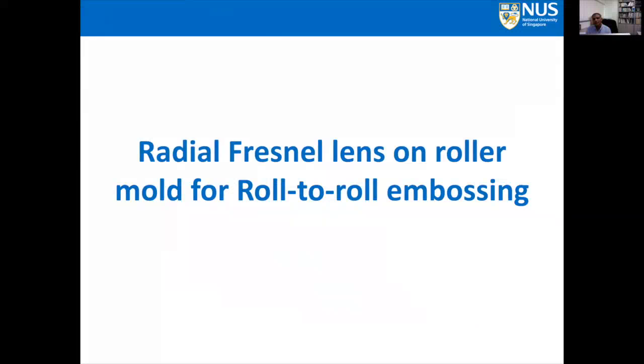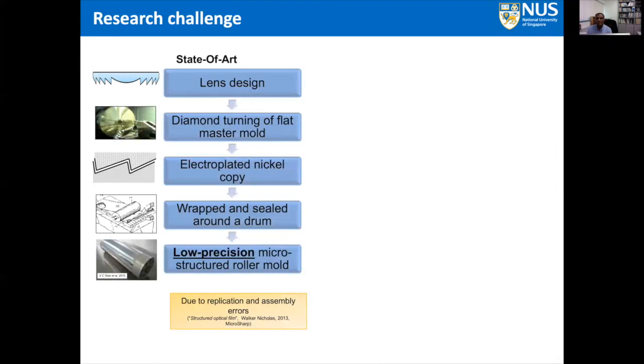So the radial Fresnel lens on roller mold for roll-to-roll embossing is something which is very important to us because now we are directly machining the Fresnel lens on top of a roller and then using that roller for embossing purpose. Therefore, we are able to produce long, continuous Fresnel lenses on polymeric films. So basically, the research challenge is that, generally, people make a lens design, then they go for diamond turning of flat master mold. Then they do electroplating, basically electroless nickel, and then of course they wrap this plate around the drum and then use it for roll-to-roll printing.